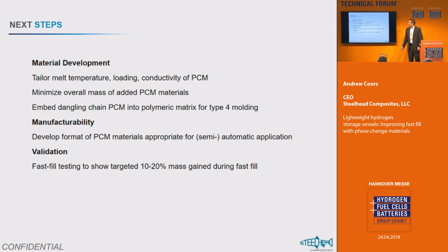So, next step on the Type 3, the aluminum liner, is we need to optimize it. Our theory shows that we can get up to 10 to 20%. We're currently at about 8% improvement. Good, probably not commercially demanded at that point. 20%, it starts getting really interesting. So in our spare time, we're going to work on that.